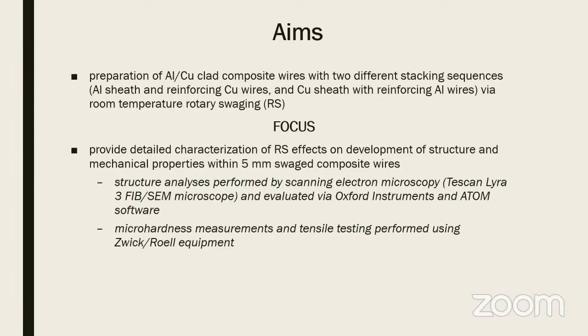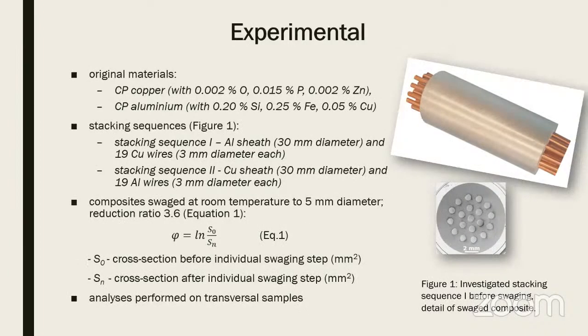As we can see here, we perform detailed structure analysis and also some micro-hardness and tensile testing. Here on figure 1 now we can see how the composite looked like before swaging. The original materials were copper and aluminum with commercial purity. We assembled the stacking sequences. First one consisted of aluminum sheet and reinforcing copper wires, and the second stacking sequence consisted of copper sheet and 19 aluminum wires. Here in equation 1 we see how we calculated the reduction ratio, which was from the original 30 millimeters to the final 5 millimeter diameter, and it was 3.6, which is quite a good deformation. And we performed all the analysis on transversal samples.